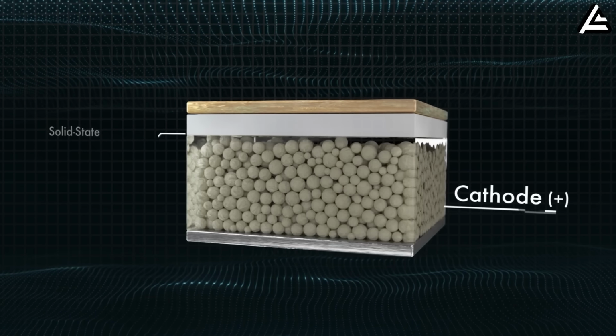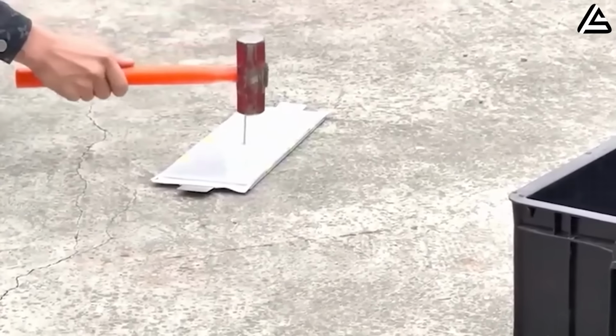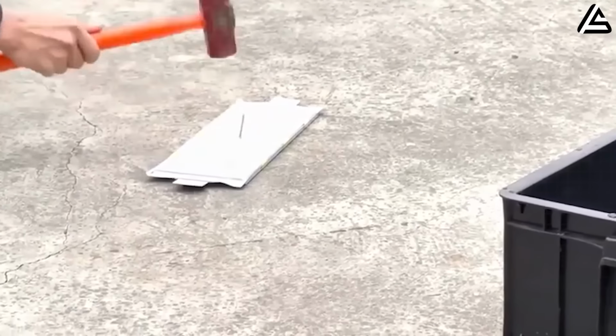Combined, this structure allows each cell to maintain stability under nail penetration tests, short circuits, or localized heating above 300 degrees Celsius, conditions that would cause catastrophic failure in conventional lithium-ion packs.